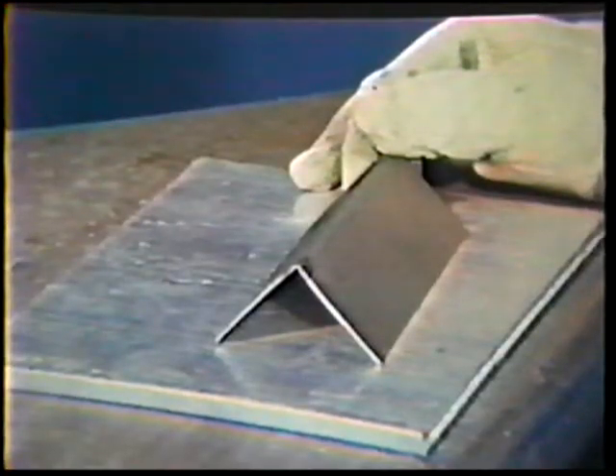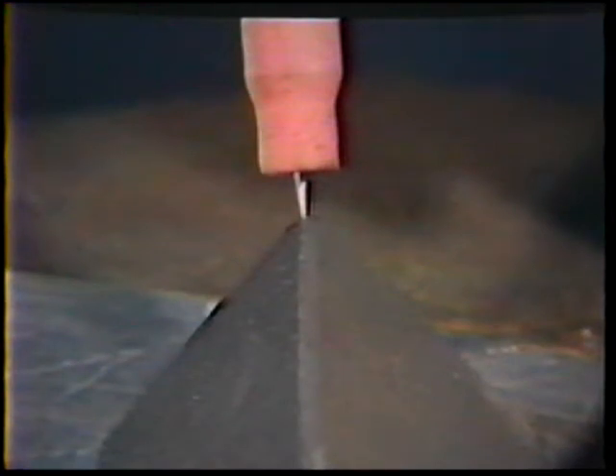Place the workpiece in the flat position with the tack weld on the left for a right-handed welder. The work angle is 90 degrees from the plane of the table with the tip of the electrode directed along the groove formed by the edges of the plate. The travel angle is 20 degrees push.